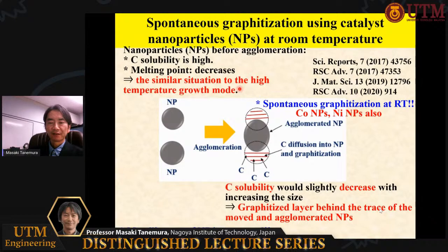During the film deposition, agglomeration of nanoparticles occurs. Then, with increasing nanoparticle size by agglomeration, the carbon solubility decreases. So, the precipitation of graphitized carbon occurs behind the trace of the moved and agglomerated nanoparticles. We observed such a spontaneous graphitization for cobalt and nickel nanoparticles.